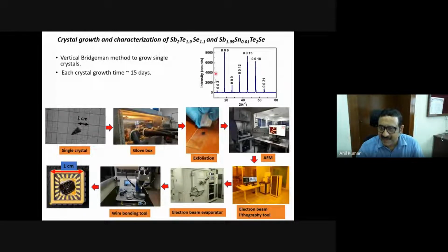So this is the X-ray diffractogram of these crystals. And this is a single crystal; again using a glove box, we exfoliate it and do AFM to estimate the thicknesses, etc. Then you do electron beam lithography, then the chromium gold deposition, and the wire bonding. Finally, your device is on the chip carrier, which is wire bonded.